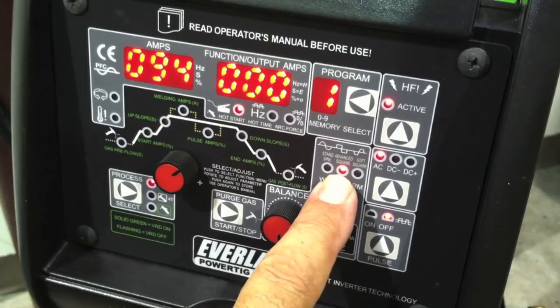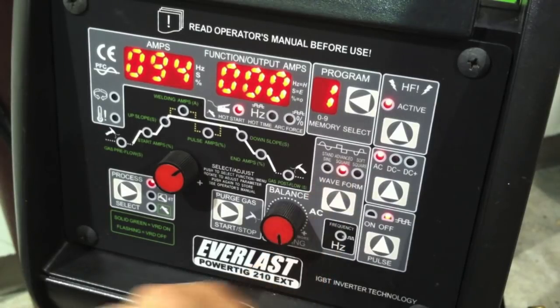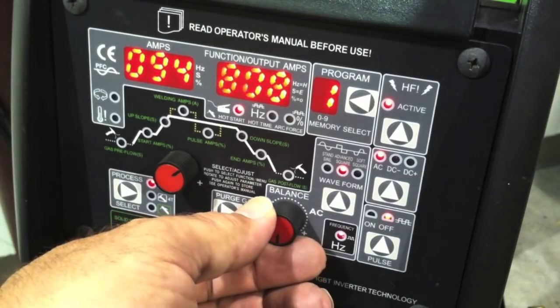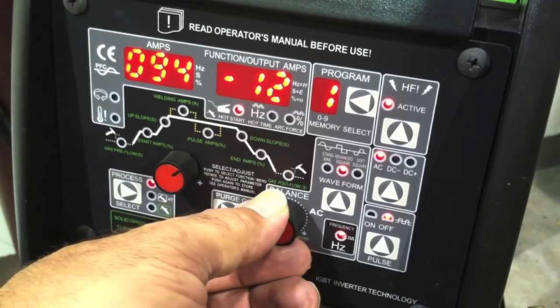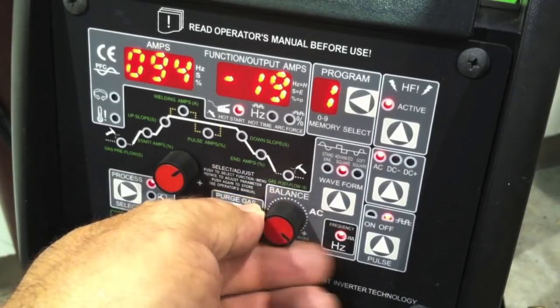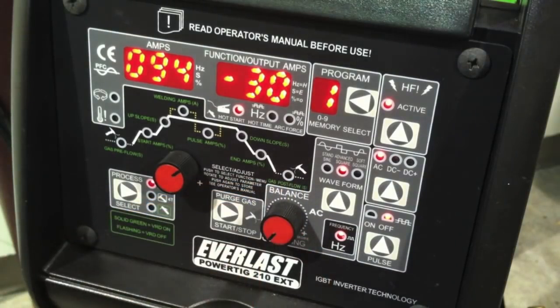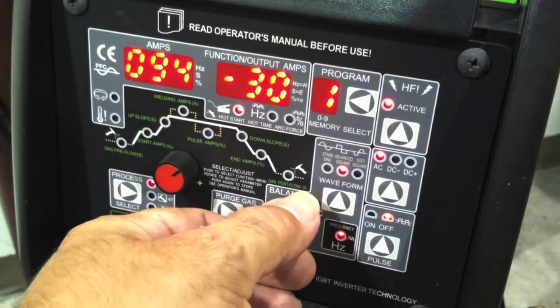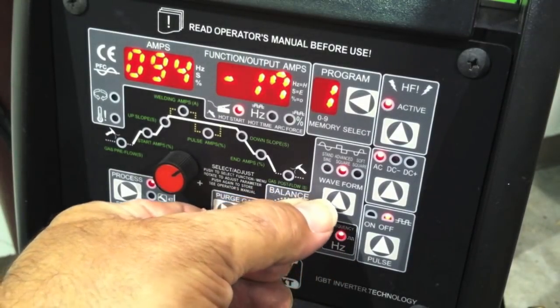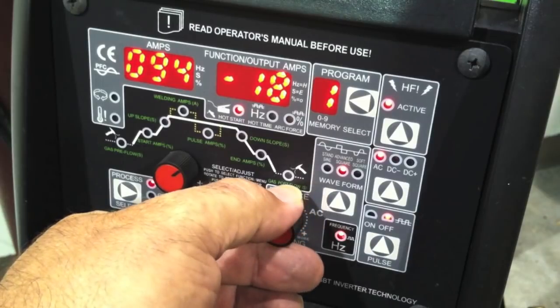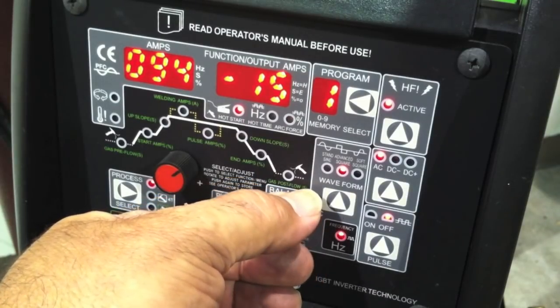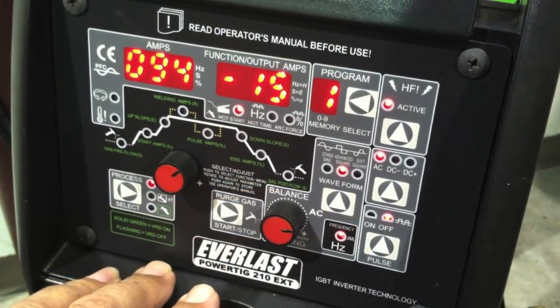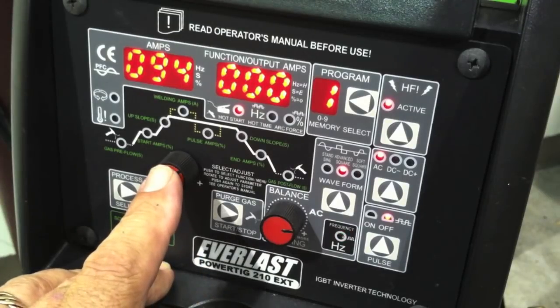Alright, the next thing, we're going to set it on AC with that button. Got three selections of waveforms, and I'm going to select advanced square. That's kind of the most versatile for me, one I like the best and you can get the most out of, it seems like. I'm going to set the AC balance. Now it's adjustable to give you all kinds of cleaning and all the way up to 80% electrode negative. But for this job, I'd rather have a clean puddle than any kind of excessive penetration or anything like that. So I'm going to set it on 15, which is the equivalent of about 65% electrode negative on other machines like a Miller Dynasty.